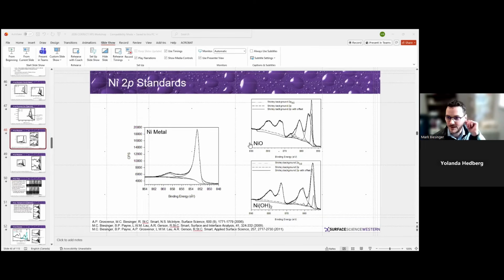Can QUASES analysis be applied to nanoparticles? I don't know if the QUASES analysis works. There are models using the kind of calculations that I showed before that take into account the spherical nature of particles. So if you have a circle, the inelastic mean free path coming from here is different, it's like angle resolved on the surface of that circle. So it changes the math. And there are some papers out there that have gone through that math where they can look at nanoparticles of different sizes and understand layering based on those calculations. But it has to take into account the curvature of those particles on average. Yeah, there are papers, people that have done that. I have papers somewhere, I can't remember who had done that, but those things are available.